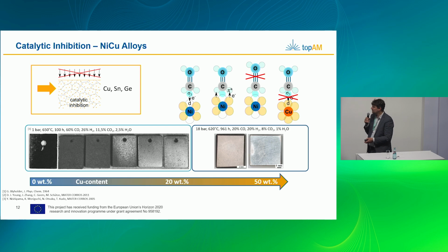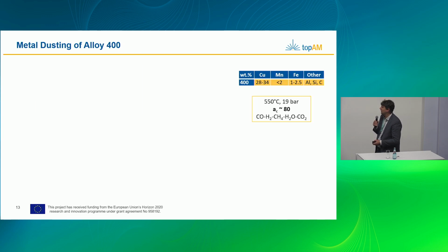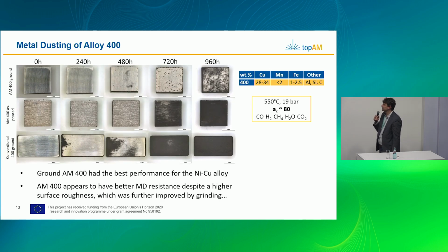This is a literature study. This was the first one from Nishiyama in 2005 that was proposed and found in Japan that when you have 20% or more copper, then basically metal dusting cannot occur anymore. So from an industrial point of view, the closest to that is basically an alloy 400. The composition is shown up here. The balance is again nickel. It fulfills the requirement of more than 20% copper. So we have about 30. We have a little bit of manganese and a little bit of iron in it. Again, we exposed it in our labs. And what you can see here on the bottom is the conventional ground material, and it's all black.